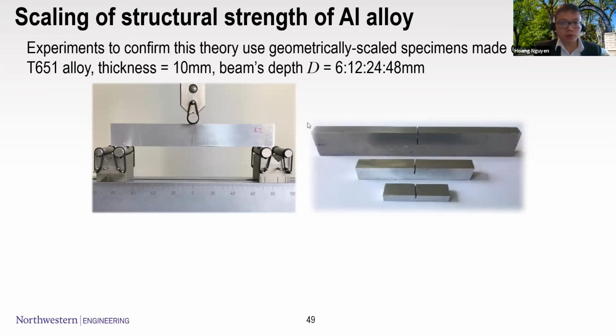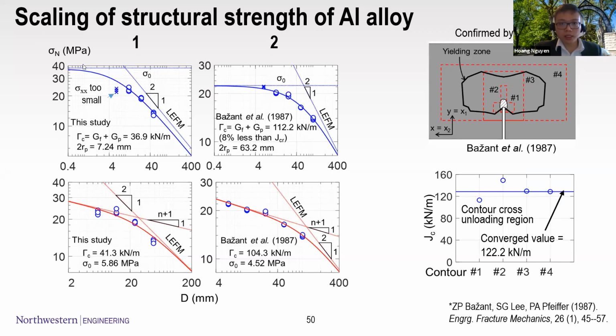And Dr. Abdullah Donmez, who is in Turkey now, helped us run the test on aluminum for the size effect. It is specifically aluminum alloy 6061-T651. And the result shows that such a law can be applied. So either you assume that you have small-scale yielding and then fit the large-size structure, or you have large-scale yielding and transition yielding, and use the transitional formula to fit the G_f. And such a G_f converges quite reasonably to the J integral, and the difference is within 10%.